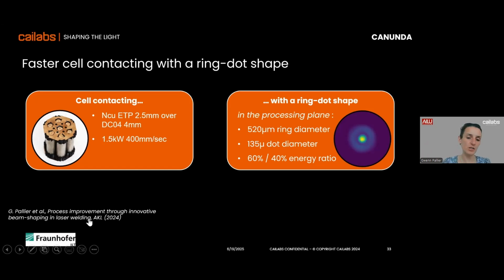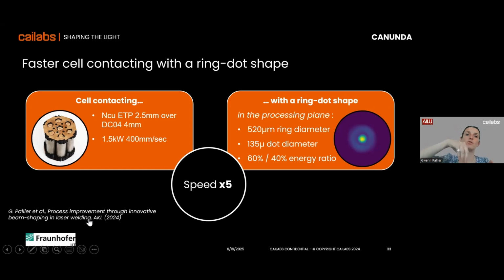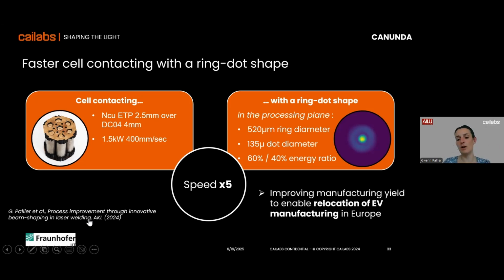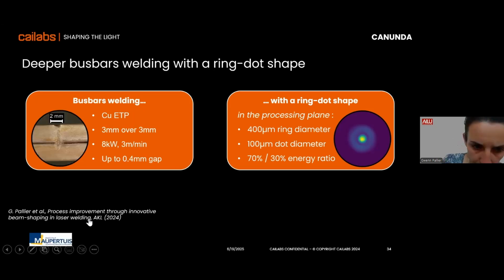So for sure, you are changing all the process parameters, but what is really important to notice is that globally, by removing the wobbling, you can globally increase the process speed by a factor of 5 because you don't have to do all those little circles. And this is quite important if you want to, again, improve your manufacturing yield.